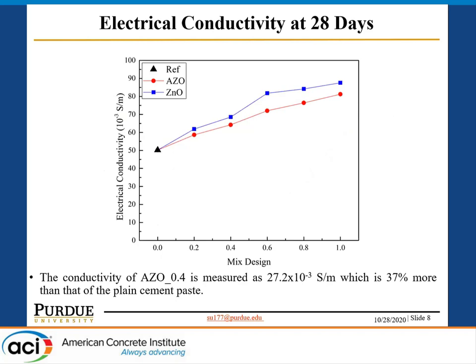Another property is the electrical conductivity, and we get this result at 28 days. The figure shows the mixture design versus the electrical conductivity. As you can observe, the red dot is the aluminum-doped zinc oxide, and the black triangle is the reference sample. The conductivity of aluminum-doped zinc oxide is higher than plain cement paste by 37%, which is impressive.